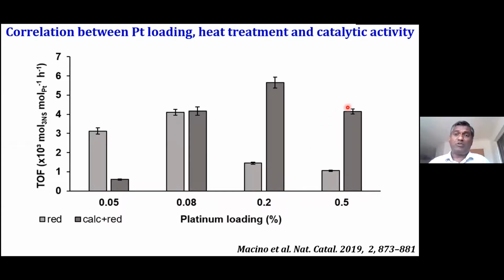A-SMSI is predominant. That's why when we calcine and then reduce, we can reduce the A-SMSI. Hence, platinum sites are accessible for catalytic reaction. So in other words, what we have done is we have reported a size-dependent A-SMSI. So for very small particles, we need a much, much higher temperature to cover the platinum nanoparticles, whereas for large particles, we need a much lower temperature to cover the platinum nanoparticles. And we have a certain loading or particle size where it's more or less the same.